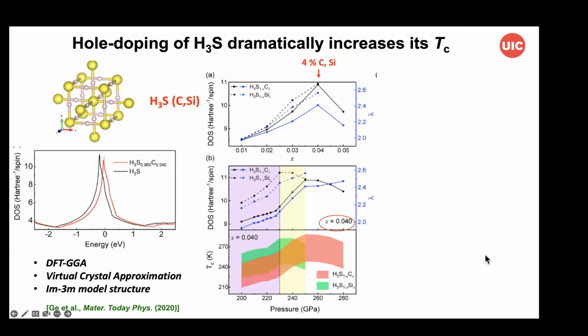So this gave rise to a very simple idea: perhaps we could use the virtual crystal approximation based on DFT, where we have these hybrid atoms and we simply adjust the impurity content, optimize the structure, and calculate the pressure dependence of the shift in the Fermi level, as well as the subsequent electron-phonon coupling and TC. What we found is that the TC and the shift maximize at a very modest doping of just 4% in the case of both silicon and carbon.